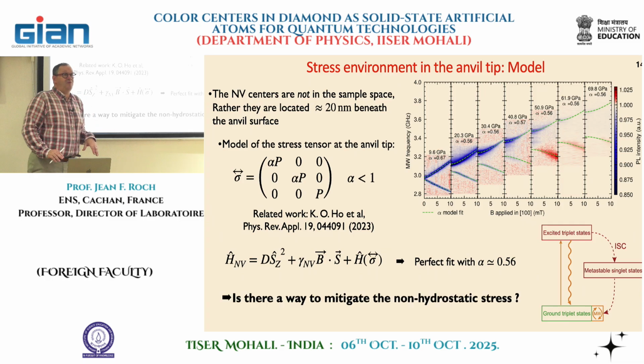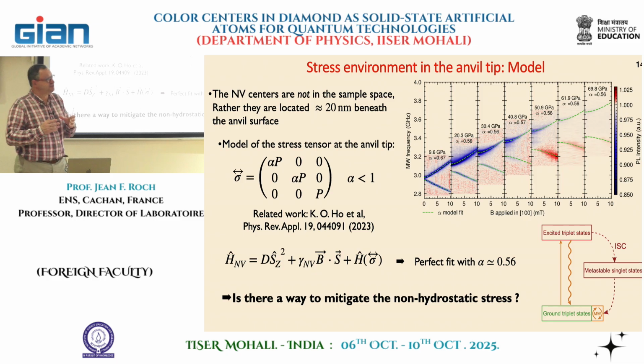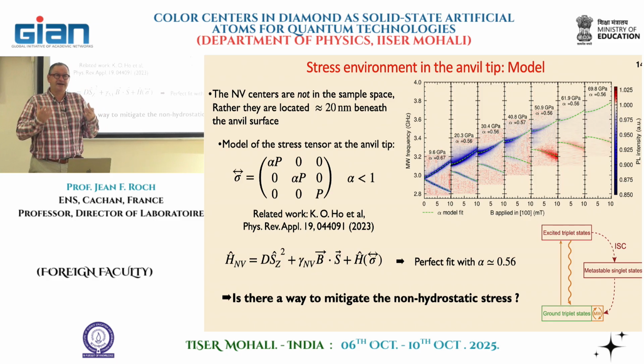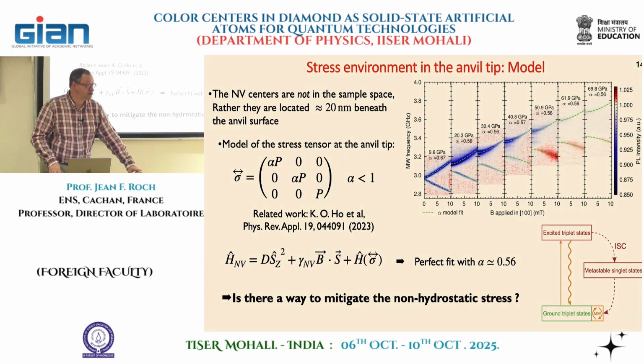So we left that aside, and we say, okay, the problem is the non-hydrostatic stress. If we are in hydrostatic conditions, we preserve the intrinsic C3V symmetry of the defect. The ms 0, plus and minus 1 will remain the good basis of the system, so we could expect that the ODMR signal will be kept even at very high pressure.